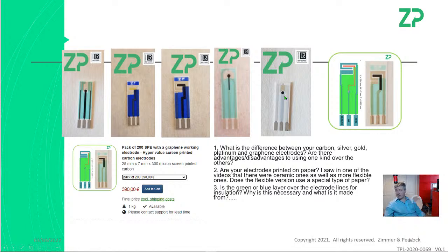If you didn't have it, somebody could put a drop onto the electrode. It could spread around, and depending on how much it spreads, you would be covering more or less electrode, and therefore your signal would be proportional in part to that coverage. It would make for a very confusing signal to interpret, because signal should be proportional to concentration. But if it's proportional to wetted area, then your signal could be higher or lower, not due to concentration, but due to wetted area.